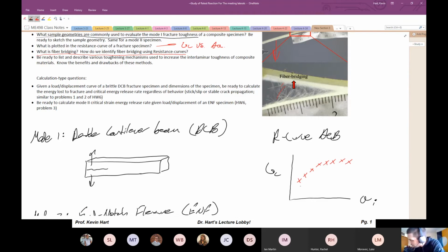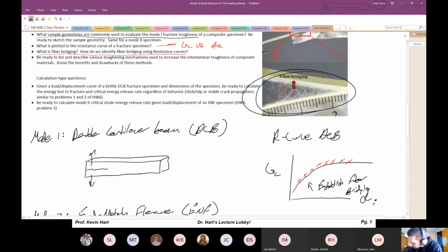So what's happening here is that we're establishing fiber bridging. Okay, so we're establishing something that looks like this. And then once I've reached this plateau here, I've got an equilibrium between the amount of fibers that are being created as the crack propagates and the amount that are being ruptured on the back end there.